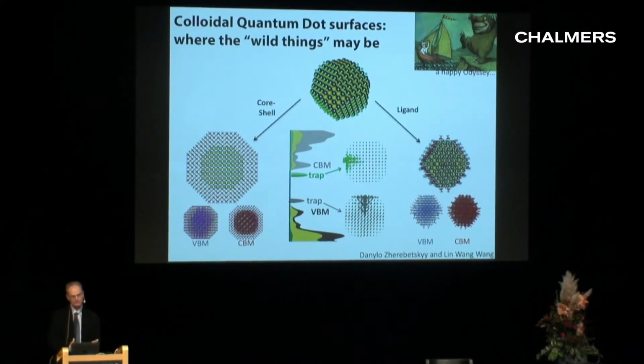So what I need to do in order to really make a great barrier, a box for an electron and a hole, is I have to surround this semiconductor with another material of a larger band gap, and that then will lock the electron and the hole in to be very tightly controlled.